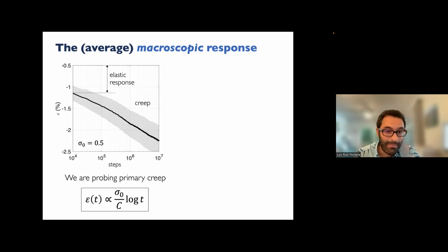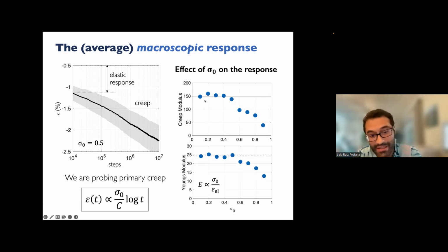So I'll show you some plots that we have about how the microscopic response depends on the applied stress. So you can quantify the macroscopic response with two parameters, for example. One is the elastic response, or the Young's modulus that you could derive from that elastic response. And the other one is the creep modulus, which is this C here in the formula that you see. So what we find is this relationship. So basically what these two plots mean is that below a certain stress, the results don't change much. You have a material that shows a similar creep modulus and similar Young's modulus. Now, when you go to higher stresses, and again, the yield stress is 1.2, you get dynamical effects that we are not very interested in investigating right now.